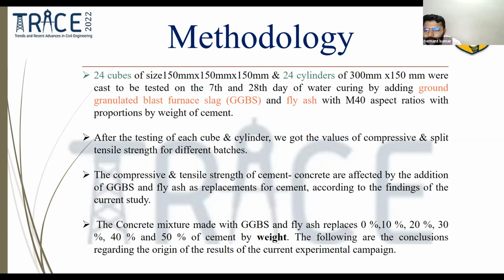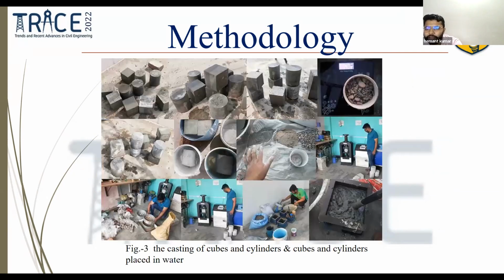The concrete mixtures were made with GGBS and fly ash replacing 0%, 10%, 20%, 30%, 40%, and 50% of cement by weight. The following are the conclusions regarding the results of the current experiment. These are some site pictures of the casting of cubes and cylinders.